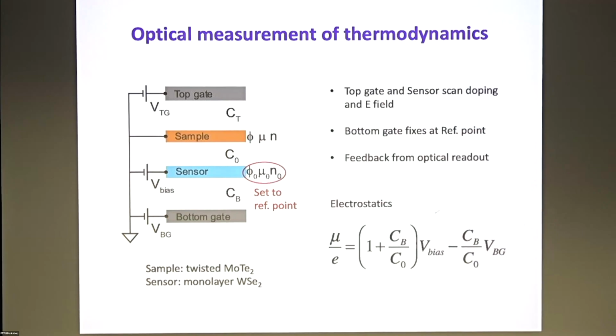Then in our experiment, we change the top gate and the sensor gate voltages, these two voltages, in order to tune the filling factor and the electric field through the sample. The bottom gate is to fix the sensor at that reference point. We use a feedback circuit for the optical readout and always try to lock the sensor at that reference point. With this experiment, you can directly read out the chemical potential of the sample from the bias voltage that you apply between the sample and the sensor, and the backgate voltage that you apply in order to keep the sensor at the reference point.